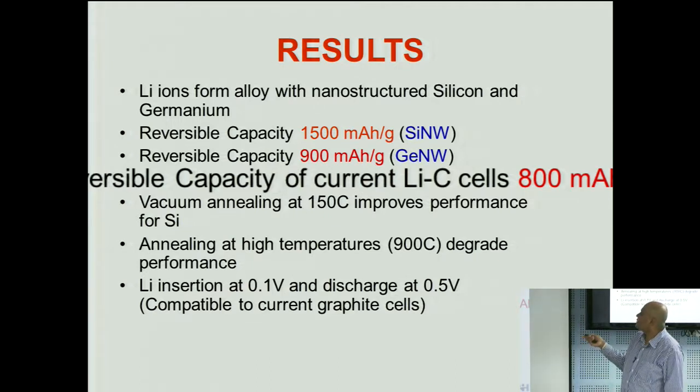So, this is what we fabricated, a lithium ion battery with silicon nanowire, and the important thing we got was that the normal lithium batteries have a capacity. What the capacity means is how much charge it holds. Our number was coming out almost double.